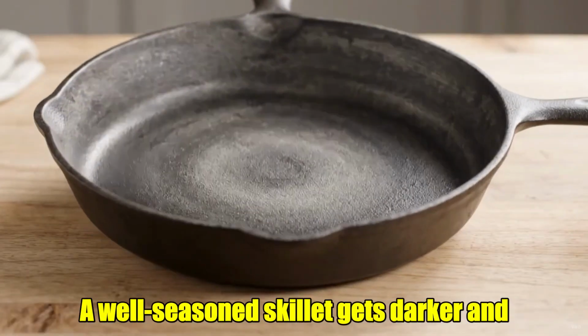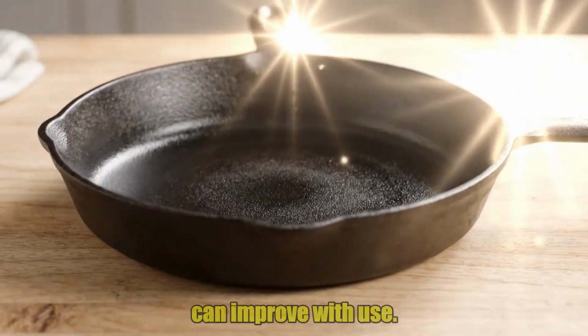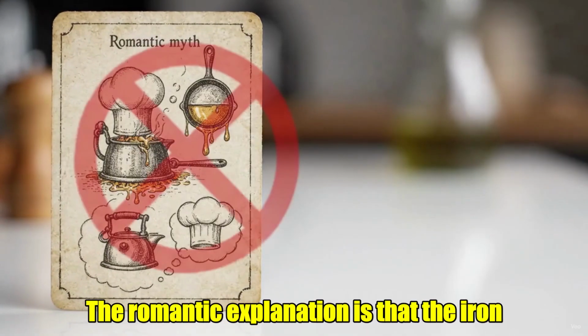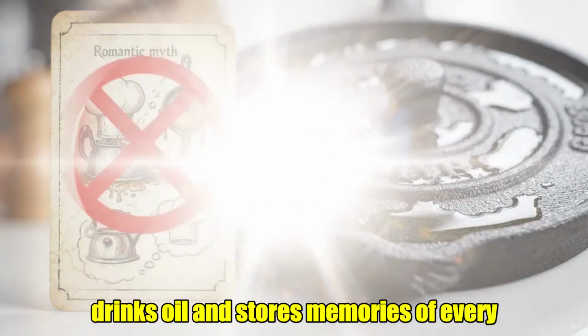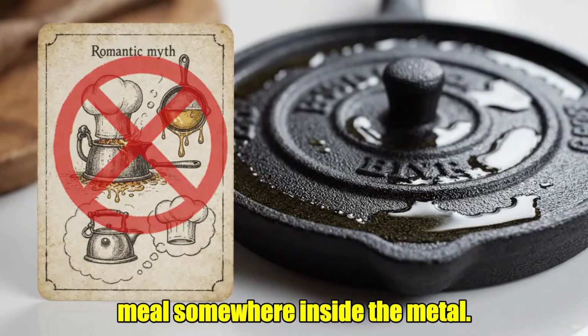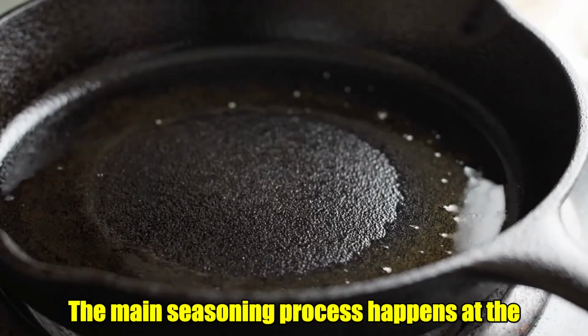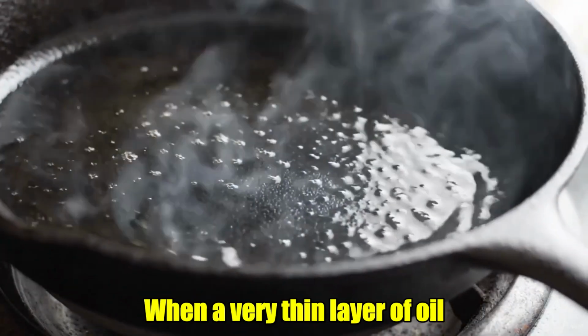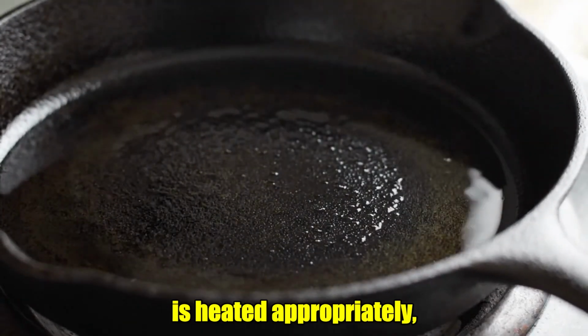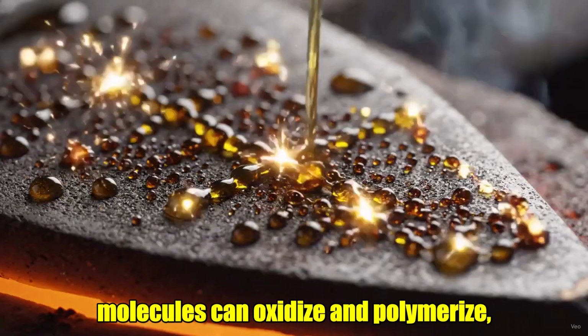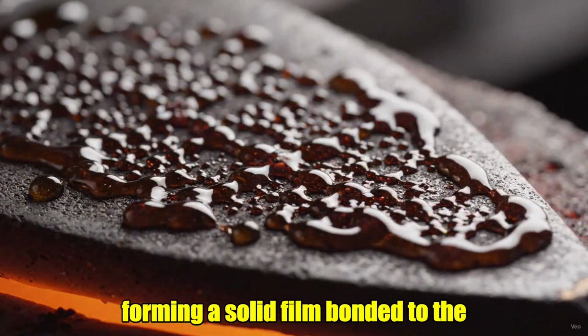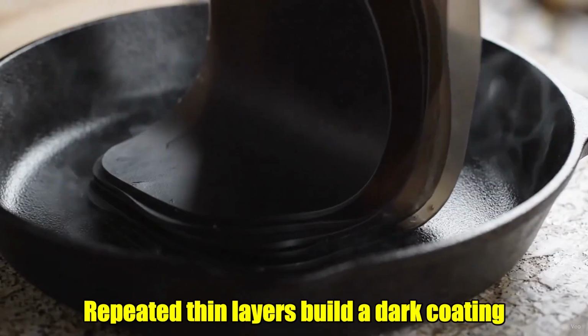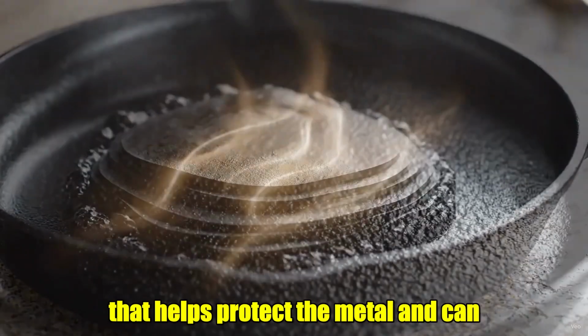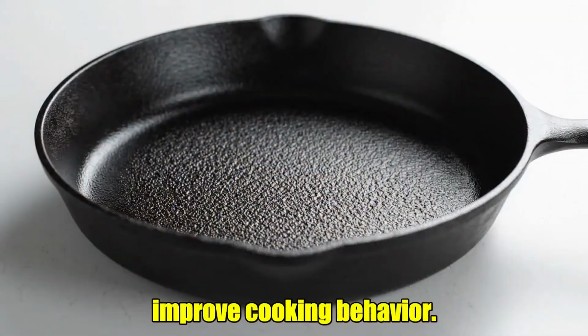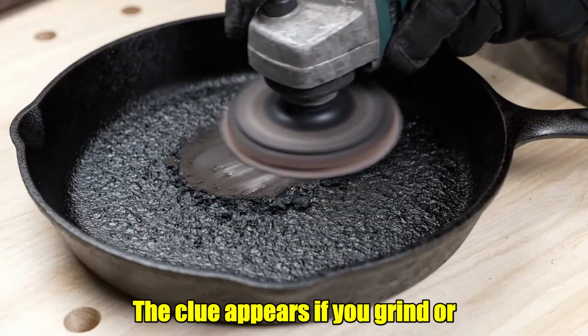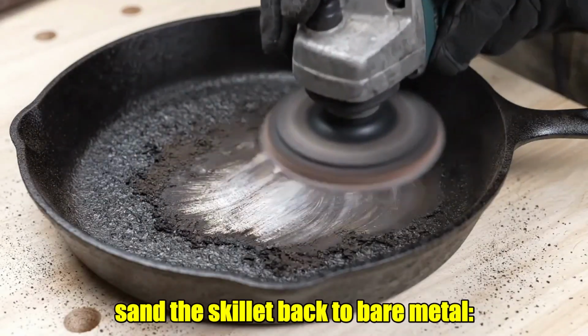Fact number 44. A cast iron skillet becomes nonstick because the iron absorbs oil and flavors deep into its pores. A well-seasoned skillet gets darker and can improve with use. The romantic explanation is that the iron drinks oil and stores memories of every meal somewhere inside the metal. The main seasoning process happens at the surface. When a very thin layer of oil is heated appropriately, molecules can oxidize and polymerize, forming a solid film bonded to the iron. Repeated thin layers build a dark coating that helps protect the metal and can improve cooking behavior.